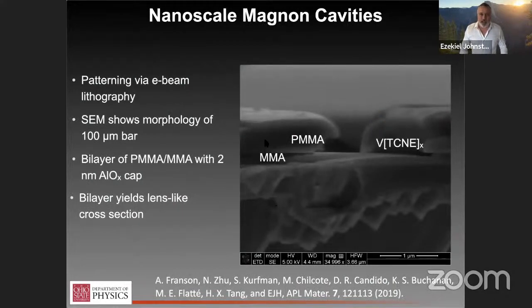So the first is that we make the pattern outside the glove box using typical, standard e-beam lithography. Then before we deposit V[TCNE]x on it, we deposit a thin aluminum oxide layer, because V[TCNE]x, it turns out, is solvent sensitive. If you don't cover the resist with something, then the solvent outgasses during growth and poisons the growth. So once we have the aluminum oxide down, we take it into the glove box, do the deposition in the glove box, and then do liftoff in the glove box.